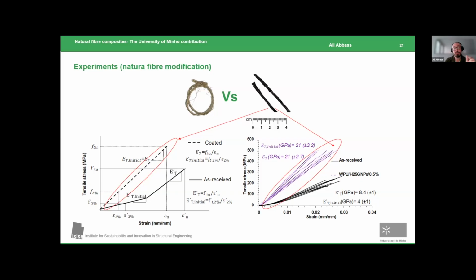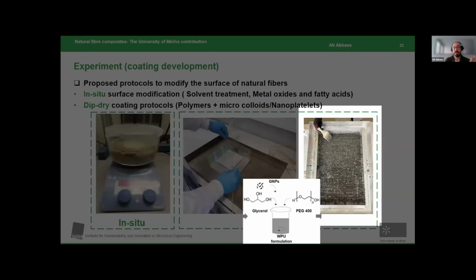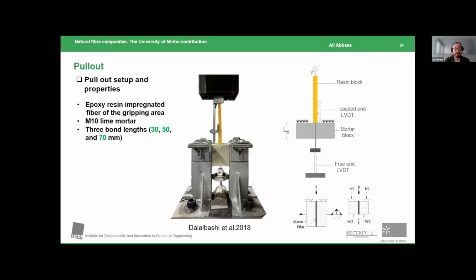Overall, we achieved five to seven times higher Young's modulus. This is very important in this sense. Based on this result, this solution was qualified for the structural characterization, as you will see in these slides. In order to examine the pull-out and the bond behavior of these nanocomposite coated yarns within the matrix, we carried out pull-out tests using three bond lengths: 30, 50, and 70 millimeters. Here you will see the setup.